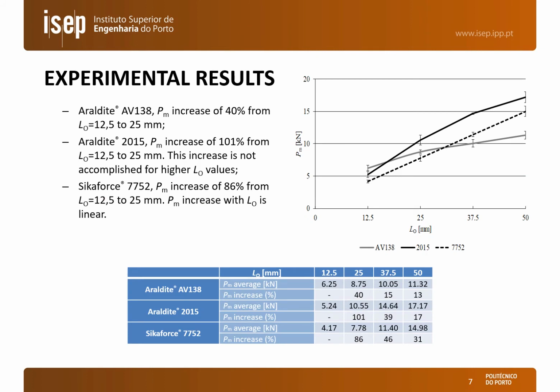Regarding the experimental results, in this graphic we can see the maximum load as a function of the overlap length for the 3 adhesives, including the standard deviation. We can see that for the AV138 the maximum load increases only 40% from an overlap length of 12.5 to 25 millimeters. For the 2015 we have a higher improvement of strength because of the ductility of this adhesive, and for the Force 7752 we have also a major improvement in the maximum load as a function of LO.